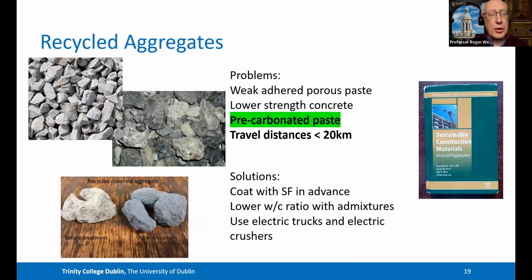So on the recycle front, there are difficulties with recycling aggregates, of course, apart from the fact that it is more porous because it has adhered cement paste on it, but it does reduce the strength as well, it tends to. Although it reduces the strength, if it's structural concrete, we hope that the concrete's not carbonated. In other words, it hasn't already absorbed carbon dioxide. Well, we might like it to, but that's for reinforced concrete. We certainly don't want it to.